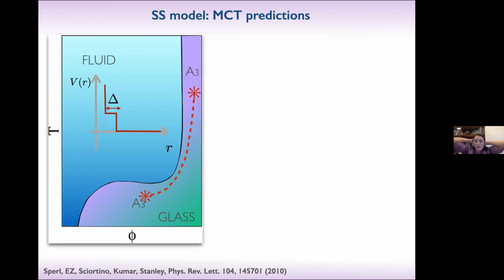We started with the MCT calculation, kindly helped by Matthias Fuchs in collaboration with Professor Stanley's group. And for a long time, we didn't find any higher order singularity, simply because we realized only much later that, if you go from the liquid to the glass, there is no higher order singularity in the typical width of the shoulder that we were probing, but actually the glass line is not going directly from the liquid, but is buried in the glass. And you have a glass line from here, from glass to glass, that has two endpoints. And actually there are two predicted A3 singularities in the square shoulder.